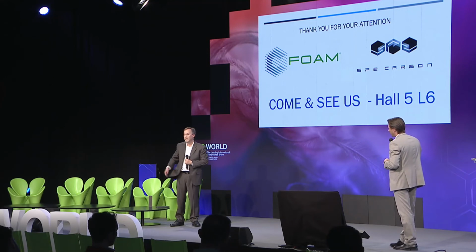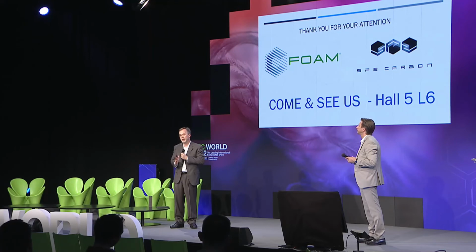Do you have something to add? I could probably add something to that last point. With our carbon foam, we're making products that are completely vitreous, that are thermally insulating, that have a thermal conductivity of 0.3 to 0.5 watts per meter K. But then we can also dope our material with graphite. We can graphitize the vitreous carbon to some extent and reach thermal conductivities of 2, 3, up to 20.